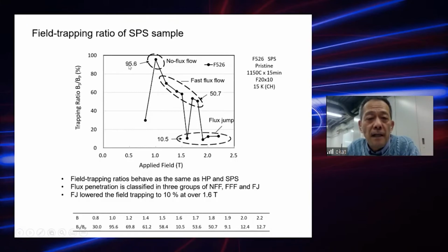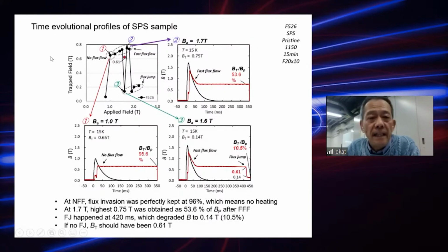So then the first flux region is here to the half of the maximum of the BP. And then the no flux flow means 95%, very excellent, in the very lower applied field region. So flux jump lowered the flux trapping to 10% over 1.6 Tesla.